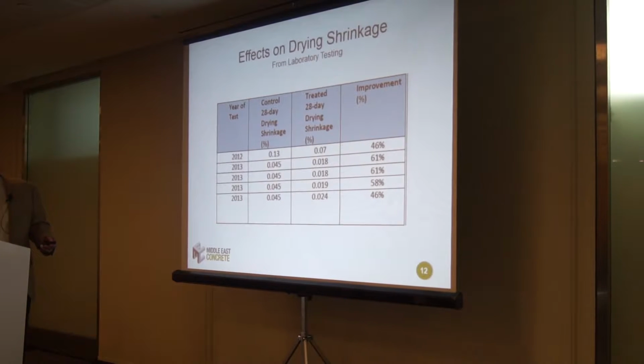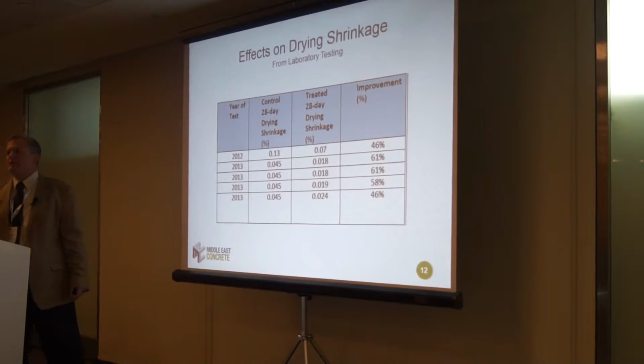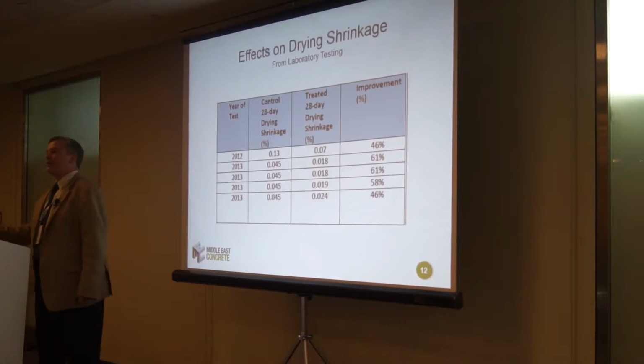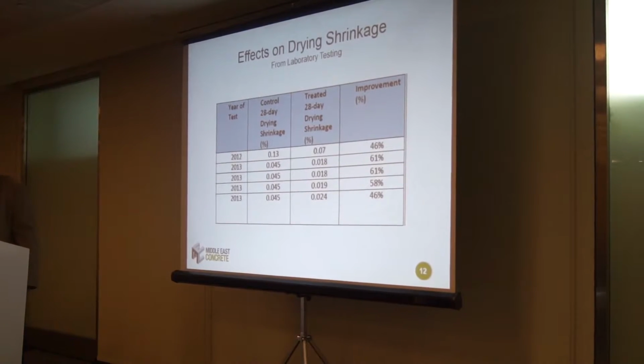And you can see that the drying shrinkage, this was a really high water to cement ratio here for the control. And you can see there was an improvement there, but it was a very high water cement ratio mix. So you have various mixes, various water cement ratios, and that's the reason for the range. So the improvement to drying shrinkage, again, is based on the permeability of the concrete itself. So the more permeable the concrete is, then the better improvement that you're going to have, to a point. I'm sure that there's concrete that is too permeable to respond well, but I haven't found it yet. So again, that's the reason for the range.